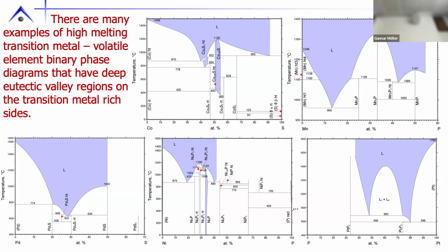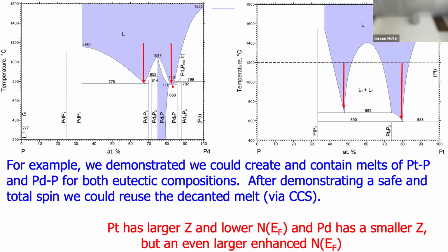But what we've been finding over the years is you can find these eutectics on the transition metal side, and as long as there's some compound on the other side, this is a valley of low vapor pressure because palladium doesn't have a large vapor pressure and palladium sulfur doesn't have a large vapor pressure, and sulfur is way over here. Okay, so we've been finding that we can create liquids that we can then drop other elements into and try to do ternary growth, or we can just access these binaries. Okay, good.